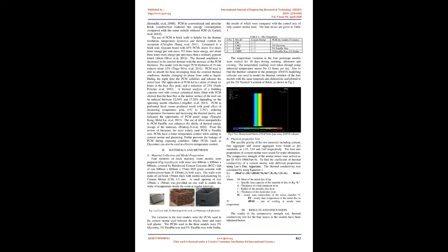Perlite, diatomite, expanded graphite, and silica fume are commonly used with PCM to prevent leakage and to attain the required strength. Hwikyong Lee et al., 2014: Highest compressive strength was obtained while mixing the paraffin wax and the hydrophobic fumed silica in cement mortar, where leakage of paraffin can be prevented by adding hydrophobic fumed silica.